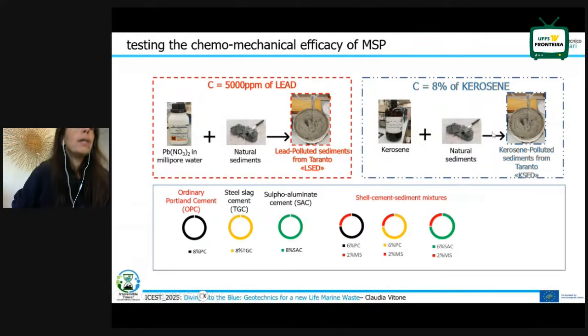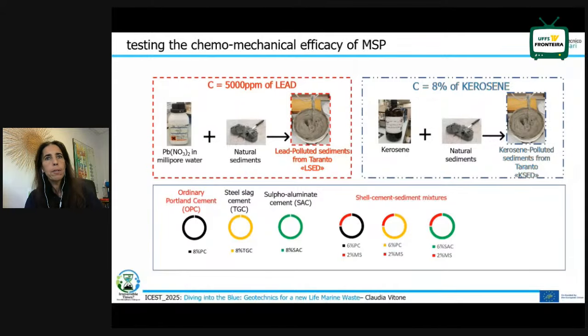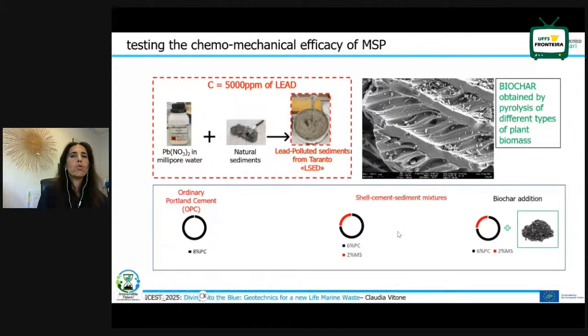So what we did essentially was to try if these solutions are also effective for contaminated sediments. In order to work in a controlled environment, we added lead and kerosene to the sediments, so we created polluted sediments artificially. Then we mixed these polluted sediments either with just cement for the control mixtures or with cement partially replaced with the mussel shell powder. But we also tried to add the biochar, which is a common adsorbent, to see if there is a boosting of this absorption capacity.